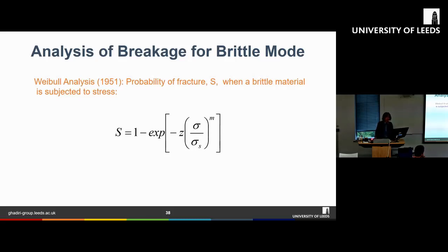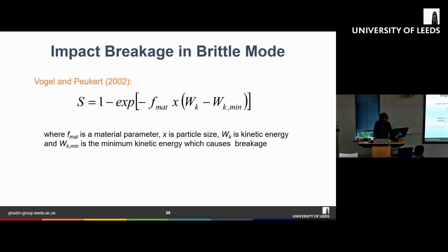So I'm going to talk about the analysis of, as I mentioned earlier, brittle materials. The breakage of brittle materials is very difficult to predict, and most people use Weibull analysis to describe it. Here is an example of Weibull analysis, which gives the probability of fracture S as a function of the stress you apply to the material and also the crushing strength of the material. We have M and Z as the fitting constants of this model.